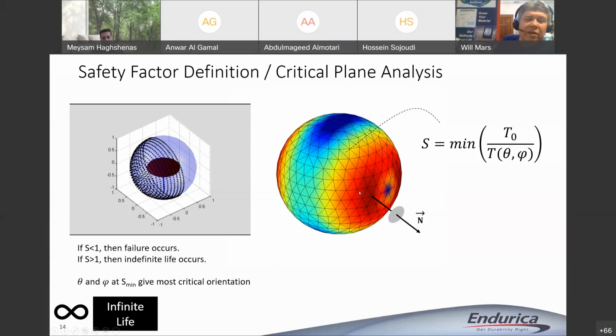Each point on the sphere represents a unit vector that is the normal to some plane that represents the plane of a crack, and you can color the point on the sphere according to the safety factor, right? So small safety factors are colored as red, and then large safety factors are going to be colored as blue. So the place where the sphere is the most red, that's the safety factor that we take, and it also predicts the orientation of the most likely crack for that particular strain history.